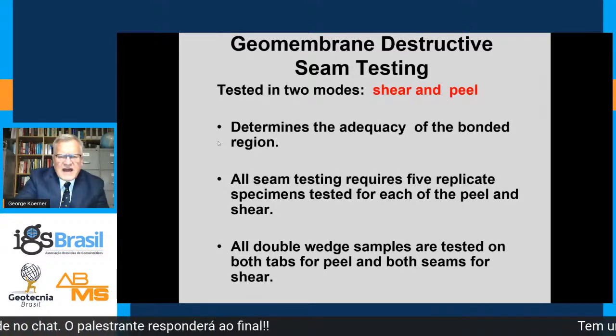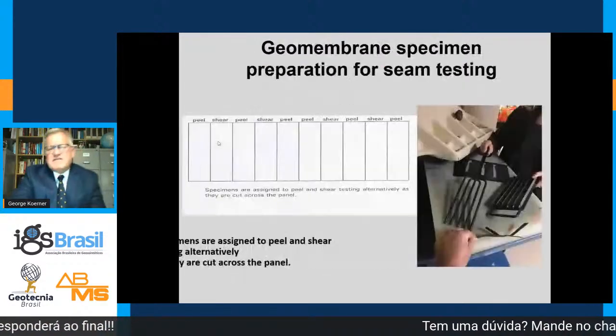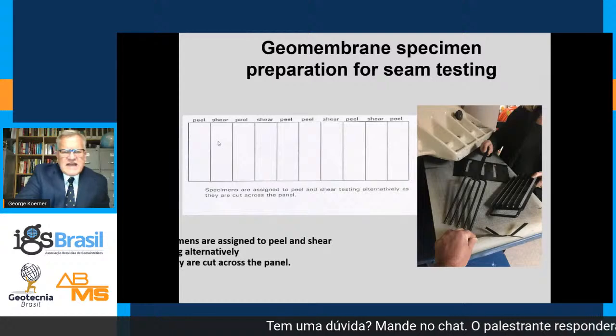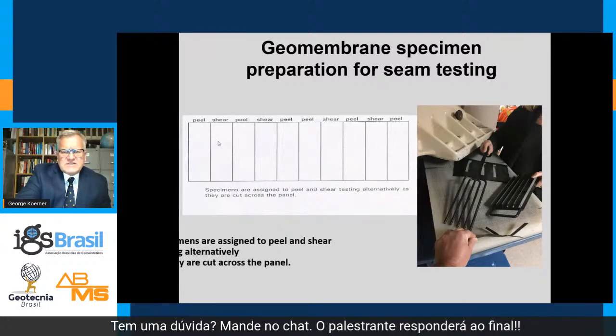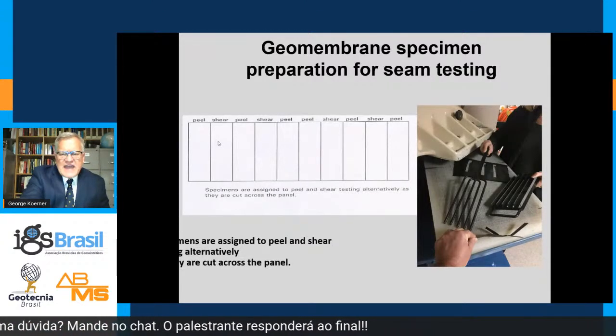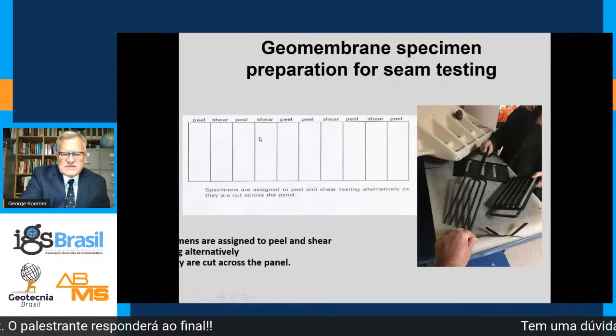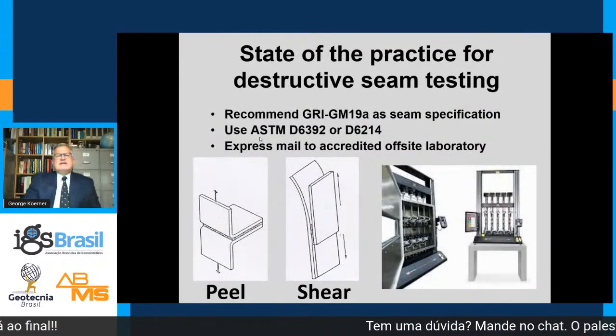It's typically 5 replicates in shear, 5 in peel. They're alternated as you see in the picture. There's typically a clicker press with a gang die, which produces these materials. It's then tested in shear and peel.